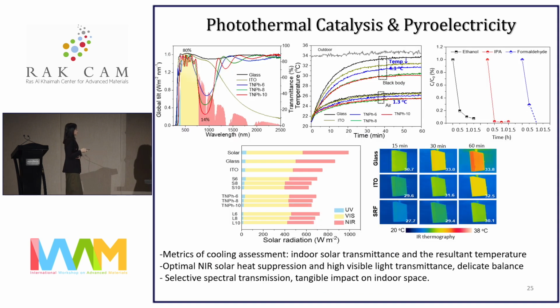So here shows all the work that we have undertaken to evaluate the cooling performance. The metrics for cooling assessment include indoor solar transmittance as well as the resultant temperature reduction. With film parameter optimization, we could suppress the near-infrared solar heat down to 14% and maintain a high optical visible light transmission of about 80%. We have achieved a delicate balance between keeping out the solar heat and letting in plenty of light into the room to ensure there is good indoor lighting.